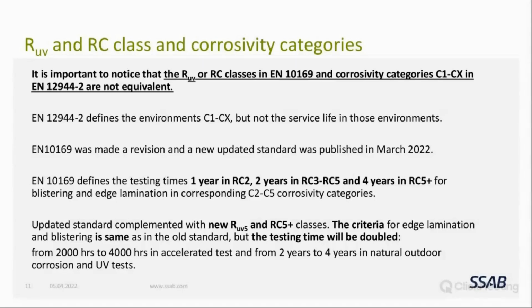Standard 10169 was revised, and a new updated standard was published in March this year. It's around now one month old, or less than one month, I would say. Euronorm 10169 defines the testing times: 1 year in RC2 class, 2 years in RC3 to RC5 class, and 4 years in RC5 plus for the blistering and edge delamination in corresponding C2 and C5 corrosivity categories.